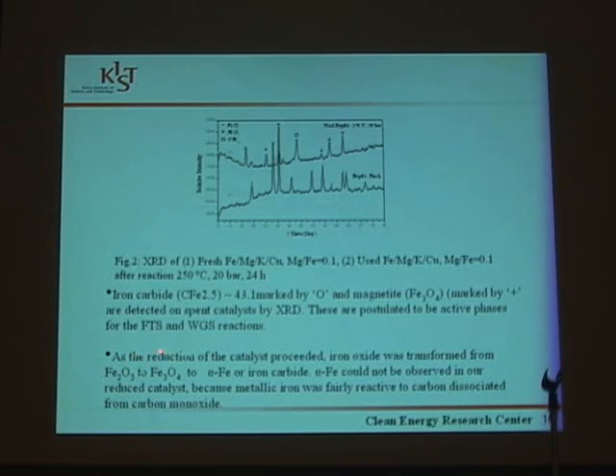So, the XRD shows that as the reduction of the catalyst proceeded, this is the iron oxide which is present in the form of Fe2O3. Then as the reduction proceeded, it was transformed from Fe2O3 to Fe3O4. So all the peaks which are marked by the sign plus are Fe3O4, which is reduced from Fe2O3 to Fe3O4, and then later on it should go to alpha Fe or iron carbide. Alpha Fe could not be observed in our reduced catalyst because metallic iron was fairly reactive to carbon dissociated from carbon monoxide.